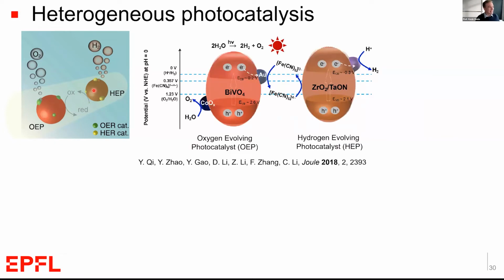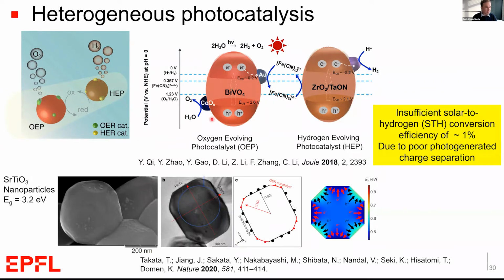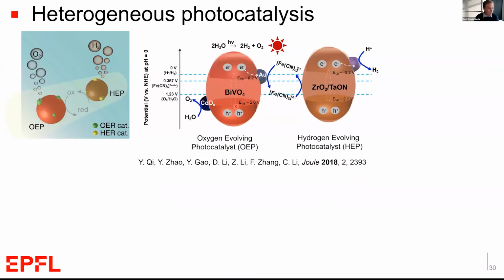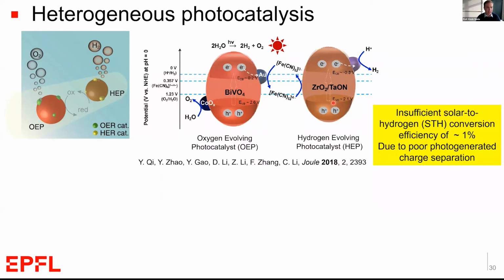One problem with using inorganic nanoparticles or microparticles for this heterogeneous photocatalytic approach is that of charge separation. In a photoelectrode, the work function of the substrate, together with the Schottky junction formed at the water interface, gives the driving force for charge separation. But in a standalone material, like in this case bismuth vanadate or tantalum oxynitride, there's not a heterojunction that can really help drive this charge carrier separation. And indeed, demonstrations of this inorganic photocatalytic approach have led to very poor solar-to-hydrogen conversion because of this poor charge separation.